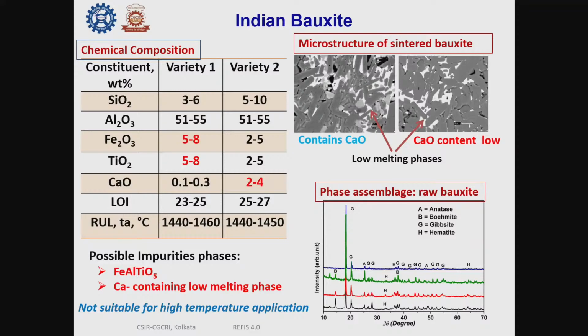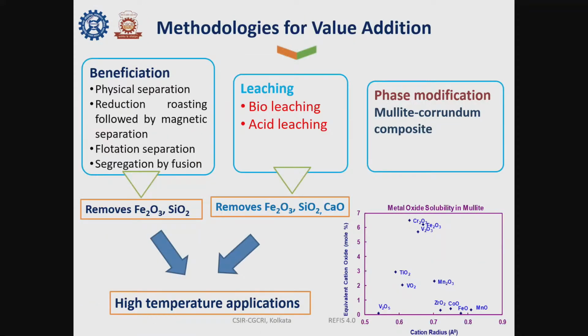We must do something for the value addition of these Indian bauxites. So there are several approaches. One is beneficiation, which can be physical separation, reduction roasting followed by magnetic separation, flotation separation, and lastly segregation by fusion technique. By this we can remove iron oxide and silica. In the leaching process, which can be either bioleaching or acid leaching, we can remove iron and silica, and also leach out the lime. And by this process, this bauxite will be suitable for high temperature applications.